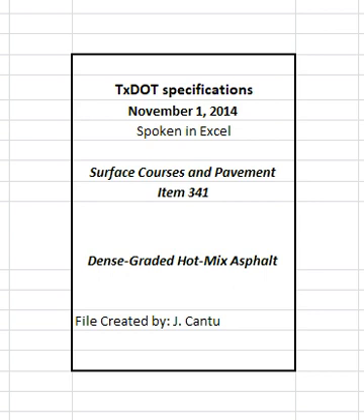4.7.3.1.1.2 Severe. Any areas that have a temperature differential greater than 50 degrees Fahrenheit are deemed as having severe thermal segregation. 4.7.3.1.2 Thermal imaging system. Review the output results when a thermal imaging system is used, and provide the automated report described in TxDOT 244F to the engineer daily unless otherwise directed.